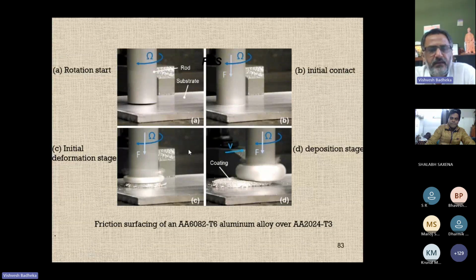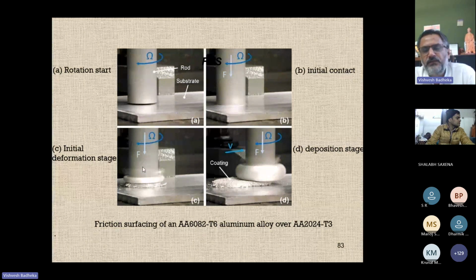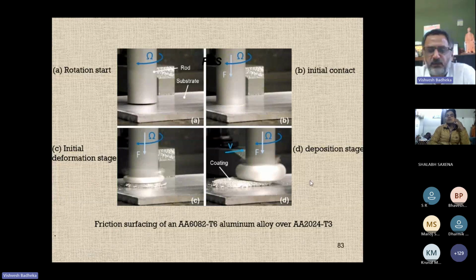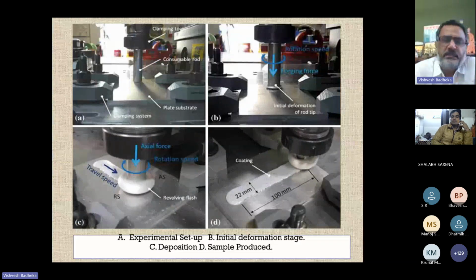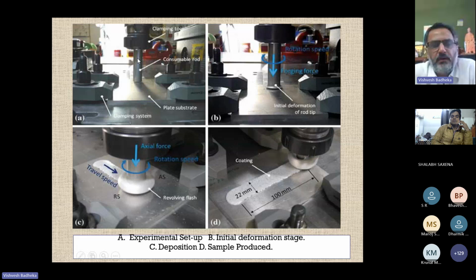Once the initial contact is there, you see the deformation starts, because the rod is under a certain force and rotates at a certain RPM. The diameter and the length of the rod are also very important. Then when the substrate starts moving, you can see the clad layer deposited on the surface. So this is the actual picture. There is a consumable rod having a certain diameter and length, and you bring it into contact with the surface. Once you do, the rod starts deforming, and once you apply the feed to the substrate plate, you see it getting deposited onto the surface.